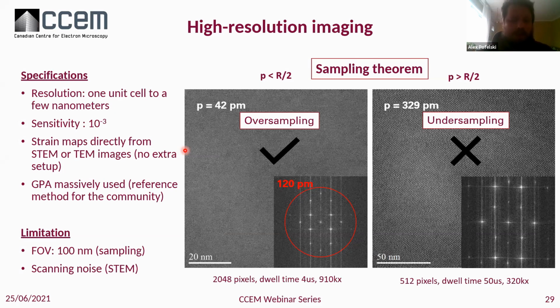Two important limitations. First, the scanning noise in STEM definitely affects the sensitivity of the method. There are some approaches, the multi-frame that we just talked about, to help with that. The second one is the field of view, and that comes directly from sampling. This is a very important thing to keep in mind: regarding the sampling theorem, a certain resolution defines a pixel size that you can use to satisfy the oversampling condition. As shown here, you need to have a pixel spacing that is smaller than half of the resolution. If you go to a higher pixel size, you're going to be undersampling.